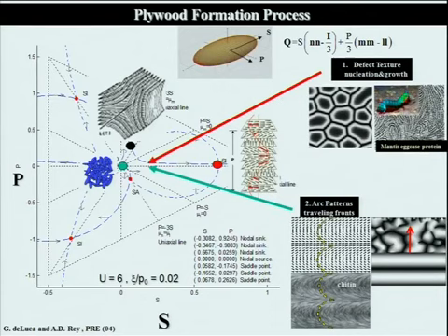And the other solution is this connection, isotropic, cholesteric, and those are traveling fronts. So you put in your solution Z minus Vt, Q is equal to Z minus Vt. You plug it into your problem, and you get traveling front solutions of this type here. This is the cholesteric phase. This is the isotropic phase.